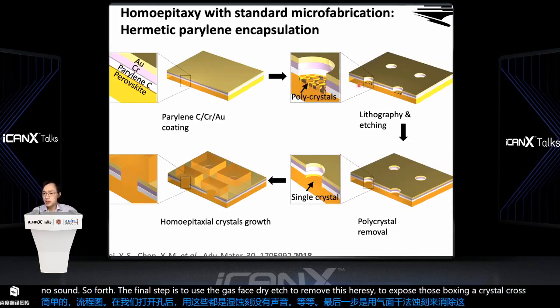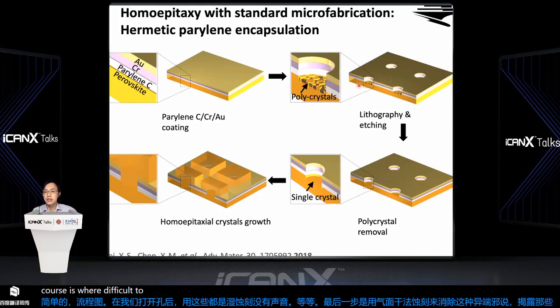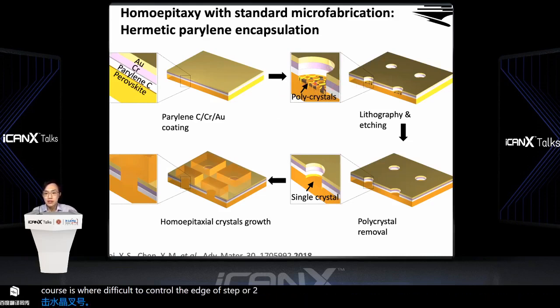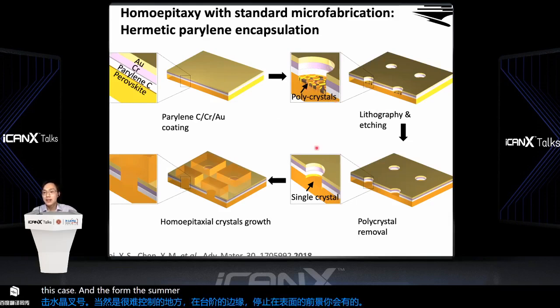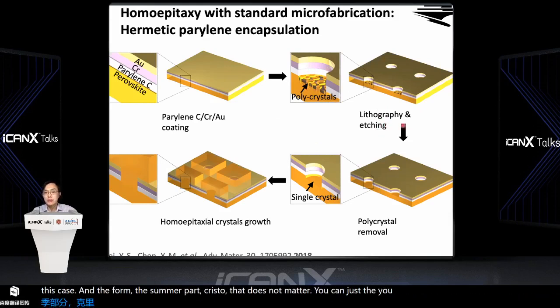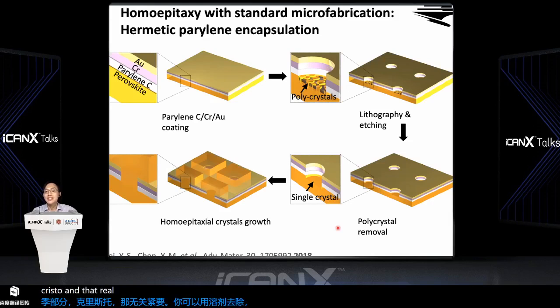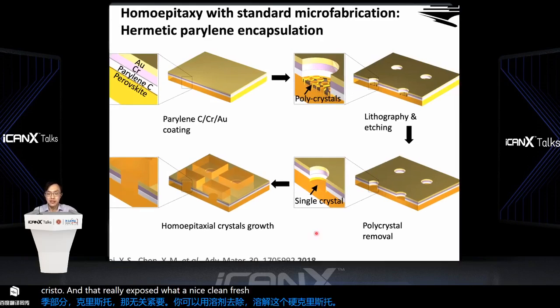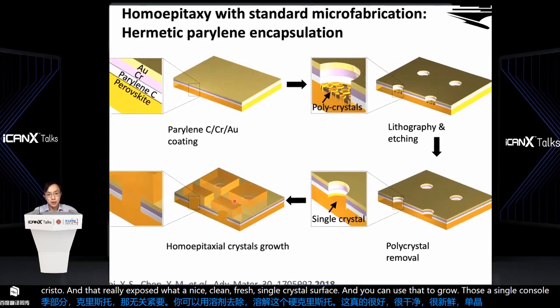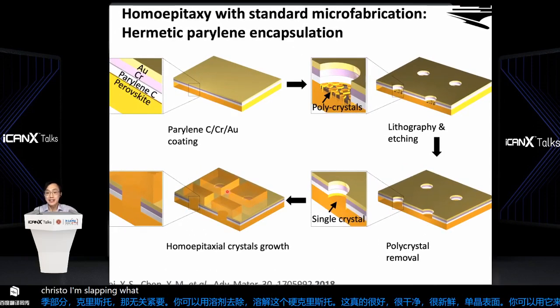And of course, it's very difficult to control the etching step to stop at the surface of the perovskite. You will have a little bit of over etch in this case and form some polycrystal. That does not matter. You can just use a solvent to dissolve this polycrystal, and that will expose a very nice, clean, fresh single crystal surface. And you can use that to grow single crystal perovskite in one. So this is the idea, the design.